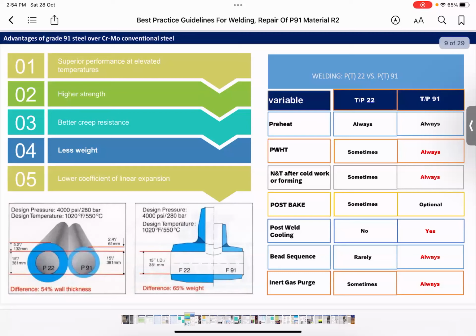So for welding variables between P22 and P91, preheat for both is required. PWHT, yeah, sometimes for some thicknesses can be waived, but for P91, it is always required. So the normalizing and tempering after cold work, it is always required for P91. Post-bake or post-heating, it is recommended for P91. It is optional, especially when you use low hydrogen designation electrodes. It can be optional, and sometimes it is used for P22 as well.